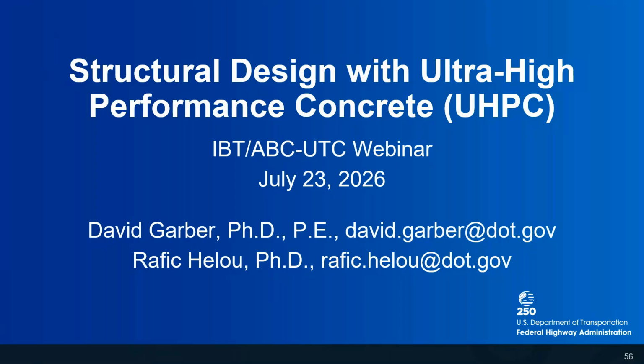So I'd say what you want to avoid is, if you're casting a structural component, you don't want to cast from both sides and have the heads of the UHPC meet in the middle. So that should be avoided. But in general, casting procedure is how you would control that. Okay. And then you said earlier about avoiding vibration.